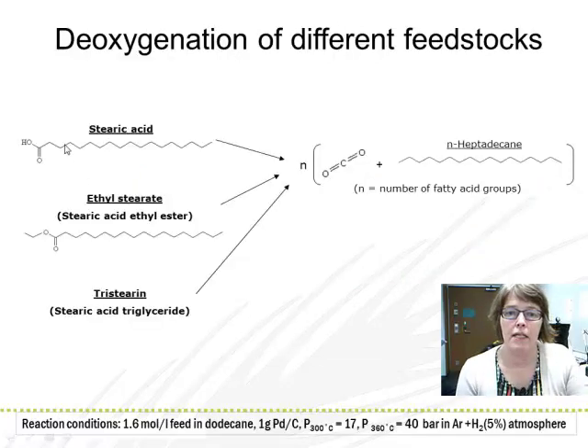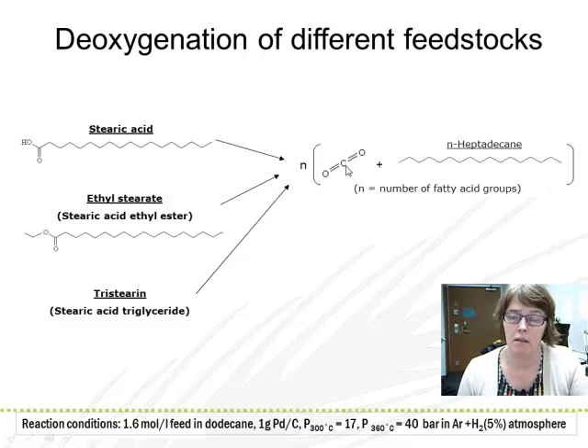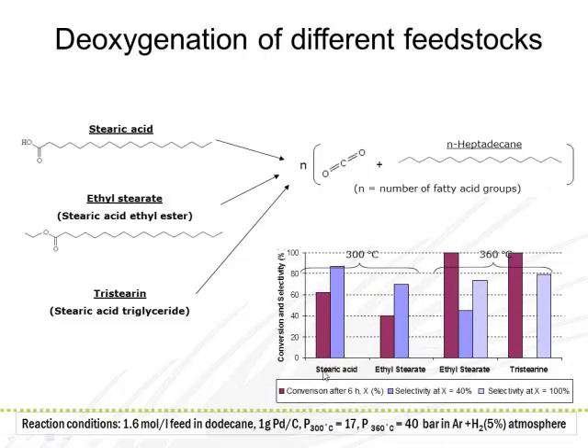We then wanted to test the effect of feedstock. We studied stearic acid as the acid, as an ester, and as a triglyceride in order to see what difference the feedstock makes. In all cases we obtained the main products carbon dioxide and C17 hydrocarbon — heptadecane. Conversion and selectivity are summarized here, and we can see that with all feedstocks we obtained quite high selectivities to the desired product n-heptadecane, either under inert atmosphere or with a small amount of hydrogen in the atmosphere.